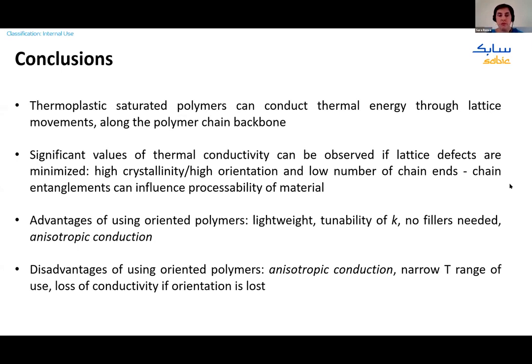In terms of advantages of using oriented polymers, for sure there is the fact that they are lightweight. You can tune the value of K depending on the stretching, and you don't need any additional fillers. And of course, the conduction is anisotropic, and this can be an advantage or a disadvantage depending on your application. And in terms of disadvantages, polymers have a narrow temperature range of use, and they will lose conductivity if the orientation is lost. So with this, I would like to conclude my part and give it back to Zhiting.